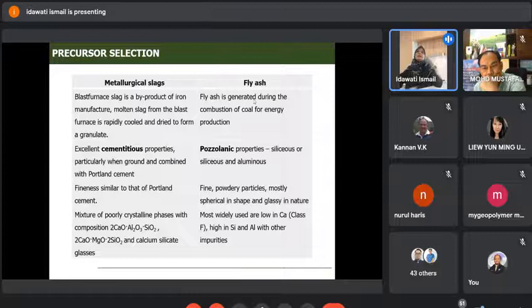I'm focusing today on the slags and fly ash. During my PhD, I used both of these materials. I'm sure by now you know what metallurgical slags are. Slags are a byproduct of iron manufacture. Molten slag from the blast furnace is rapidly cooled and dried to form a granulate. So slag or blast furnace slag is excellent. It has excellent cementitious properties, meaning it has high calcium.